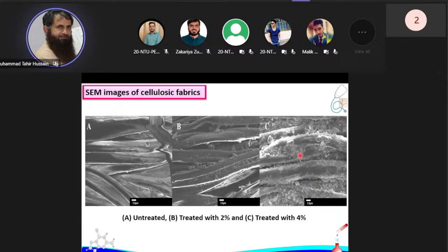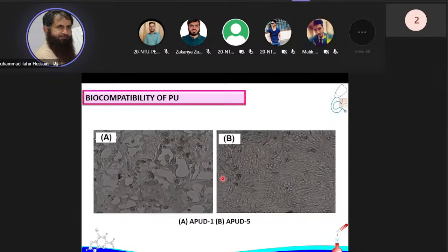the fabric. So we also studied the biocompatibility of polyurethanes. We added these dispersions along with the blood of humans, and we found that these are biocompatible. And this material that contains a small amount of the chitosan and the curcumin showed less biocompatibility, but with the increasing concentration of chitosan and curcumin, the biocompatibility of the material has increased.